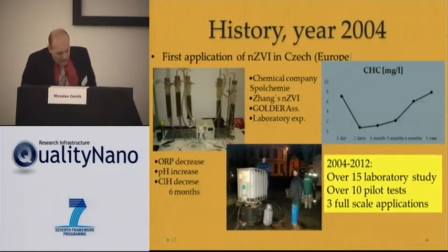But my talk is about the application mainly, so we started in 2004, where we did the first application outside of the United States, and we did some very old-fashioned laboratory experiments at the time, and then we did some simple application of the particles which we got from the Golder Associates and particles according to Professor Zhang's recipe. And we saw that we are able to reduce the concentration of chlorinated ethenes for at least 6 months.